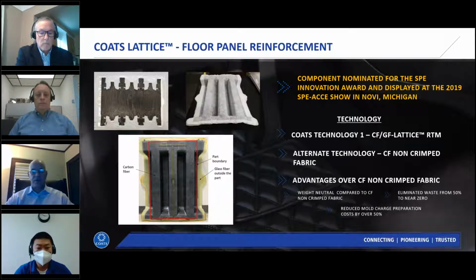Versus steel, this structure reduced crash intrusion into the passenger cabin by 45%. We converted the 2D preform into a 3D preform prior to loading in the HPRTM mold. To save cost, we included fiberglass in the outer edges of the part that are trimmed off. The project resulted in a 50% reduction in the 3D preform preparation steps and reduced waste from 50% to 0.